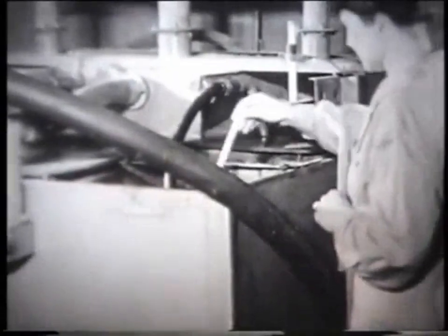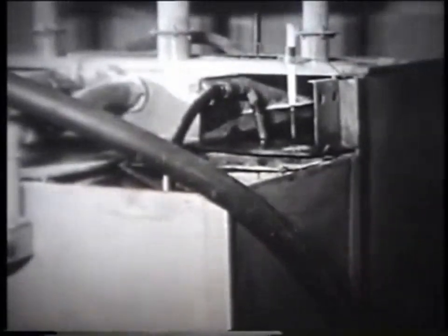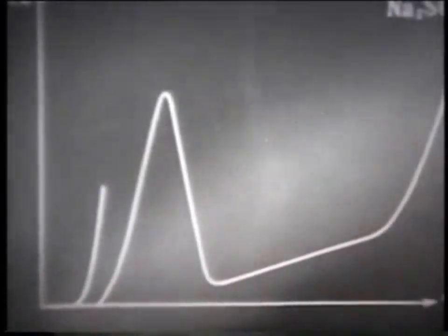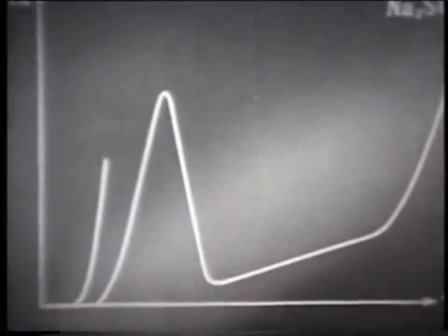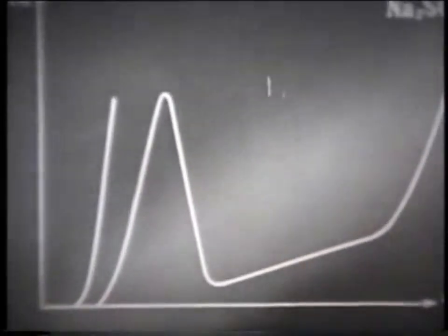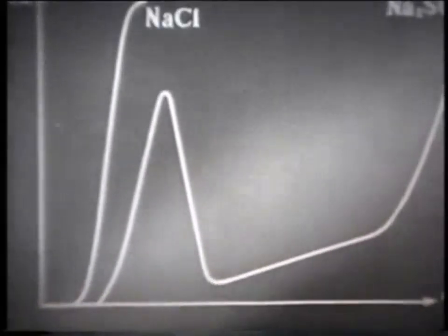The most widespread are aqueous solutions of sodium chloride. Chlorine ions activate the dissolution process. Pitting in such electrolytes almost does not occur or has a weakly pronounced character. Thus, the composition of the electrolyte has a significant impact on the performance of the process.